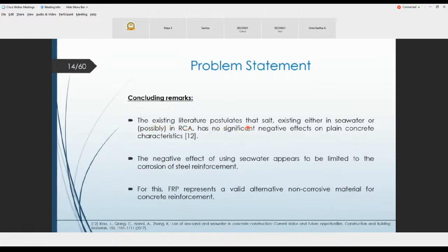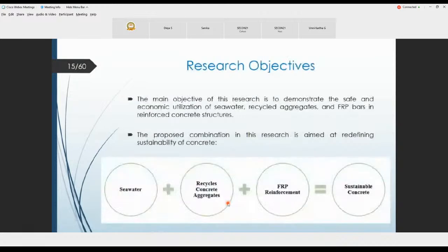The existing literature postulates that salt existing either in seawater or possibly in RCA has no significant negative effects on plain concrete characteristics. Also, the negative effect of using seawater appears to be limited to the corrosion of steel reinforcement. For this, FRP represents a valid alternative, non-corrosive material for concrete reinforcement.